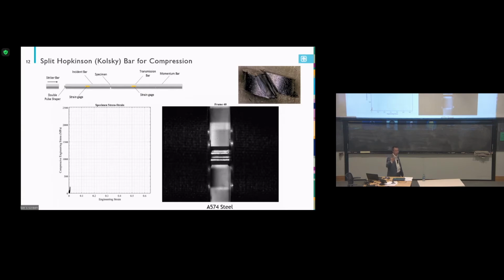But how do we know what exactly happened in this sample? We use high-speed cameras. We heavily rely on them. We have multiple high-speed cameras that can run up to 1 million frames per second, so we can exactly capture what's going on. Most of the video I presented was taken by the high-speed camera. So even though it's very, very fast, you can still see how the specimen got broken. Here is an example of A574 steel.